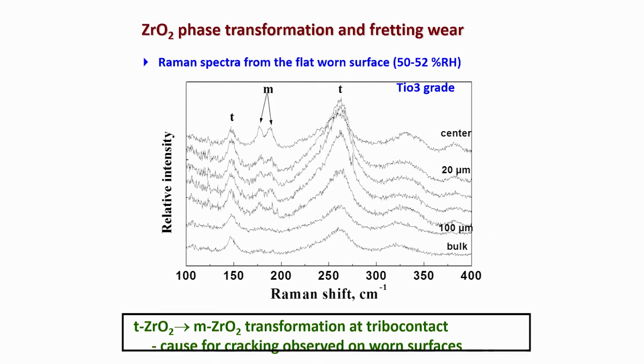Now, as I said before, the tetragonal to monoclinic zirconia transformation leads to toughness increase around the crack tip. Now, we have observed that there are clear signs of microcracking on the wear surfaces, and also the cases where we have observed significant microcracking also experience higher wear, or higher material removal, or low wear resistance. Therefore, we are interested to know whether this phase transformation also takes place on the wear surfaces.